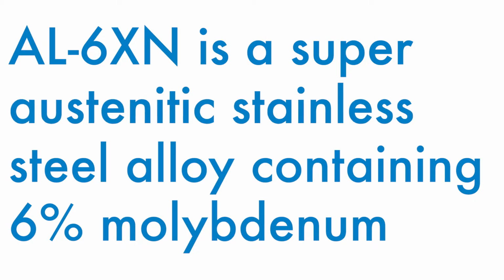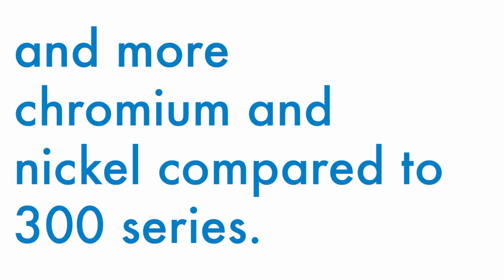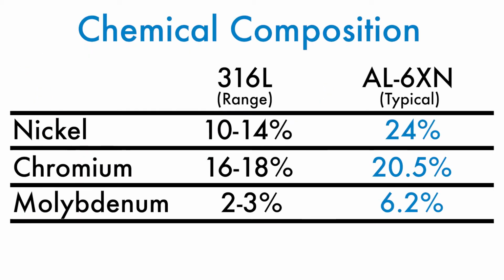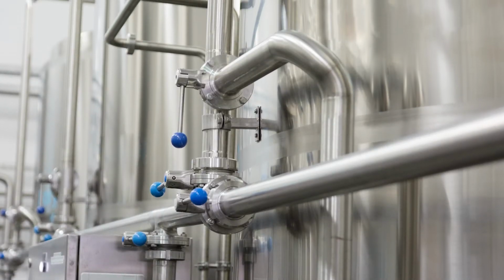To solve this problem, CSI recommended the plant use a more corrosion-resistant metal, Al6xN, on all their process lines handling high chloride solutions. Some lines needed no change. Al6xN is a super austenitic stainless steel alloy containing 6% molybdenum and more chromium and nickel compared to 300 series, which means it has a higher corrosion resistance than the 300 series metals the company was previously using. Making this change would extend the life of their system and reduce unplanned downtime.